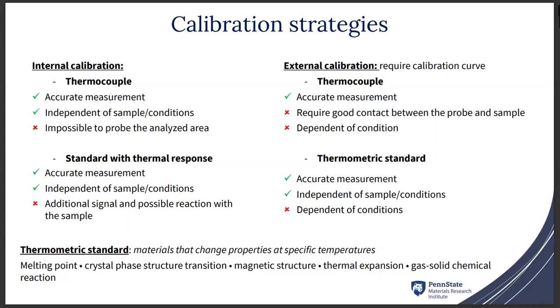One of the issues with that is it requires a good contact between the probe and the sample, and it's highly dependent on the condition. So if you change the flow rate, if you change the gas, then this calibration might not be valid, which is true for any external calibration.